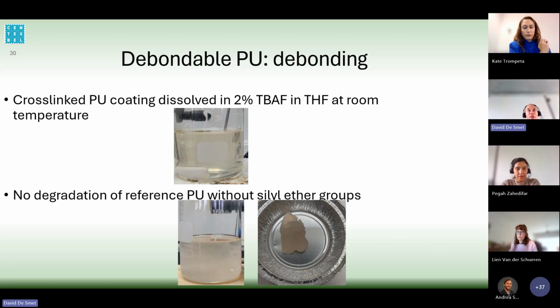In case you have a hydrophilic polyurethane, then it's possible to use water or an alcohol, because the solvent has to give accessibility to your fluoride ions to the PU backbone. So therefore, it's important there's some, I would say, compatibility of the solvent with the polyurethane. If you just look at the picture, you can see that the cross-linked PU coating is completely gone. So it's completely dissolved into the solution.